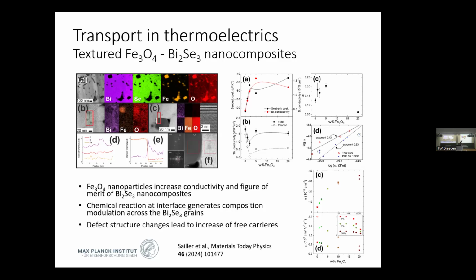Because we have compositional gradients, this balance is unnaturally biased, creating two things, which we then could rationalize with the help of calculation factors. The defect structure, this balance between antisites and vacancies, gets disrupted, creating, in all cases, an increase in free charge. They are all donor type. The imbalance results in donor type defects, creating an excess of carriers. So we ended up doping our materials without doping it.